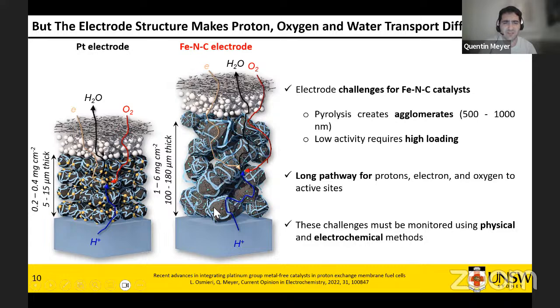Particles may not be very uniform in size because of how they're agglomerated. So you may have some very loose ionomer interactions with your particle, with your active sites. As a result of this, because you put something very thick, you may end up with a very long pathway for your protons, electrons, and oxygen to the active sites. And you end up with something which is between 100 and 180 microns thick, which is 1 to 6 milligrams per square centimeter. 100 microns is the thickness of a human hair. And in chemistry and in most chemical synthesis, when you start to be able to see things with your own eyes, then you're going to have challenges and things are going to get quite complex.